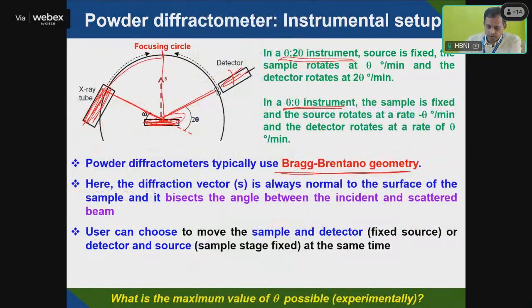Okay, so if you see here, this is your source, this is your sample, and this is the detector. If the incident line is completely transmitted, it will go like this, but it is diffracting from here. So the angle 2 theta is from this transmitted beam to the detector. This is 2 theta. If you take in between here, this will be theta, this will be theta. Instead of taking this measurement, since both are rotating, the sample is rotating, what we get from the software is 2 theta instead of theta.